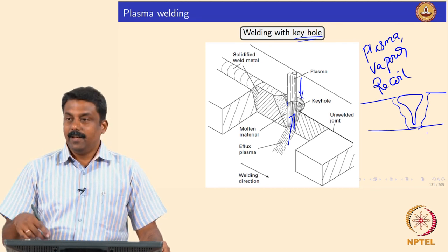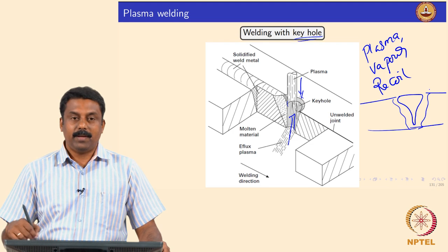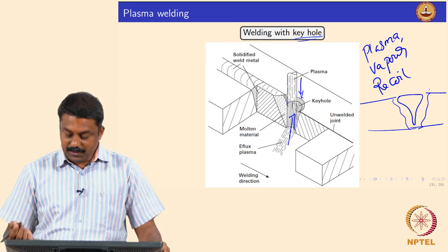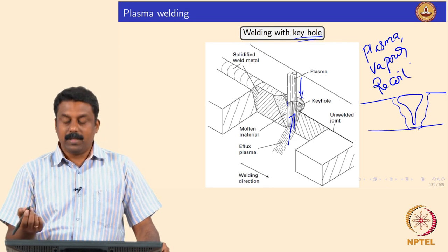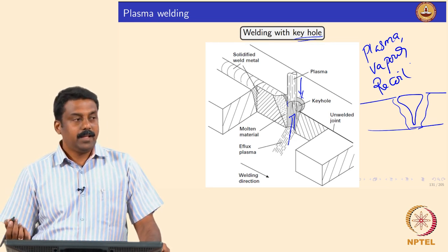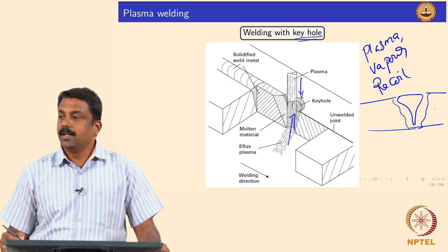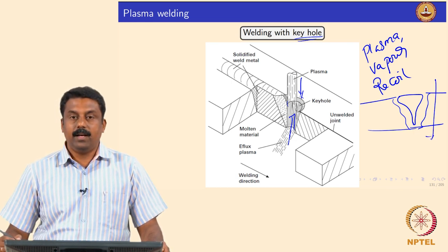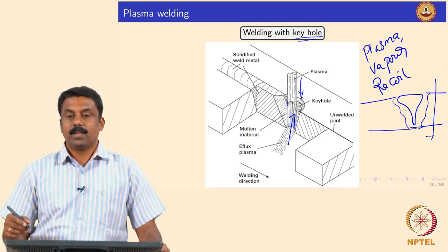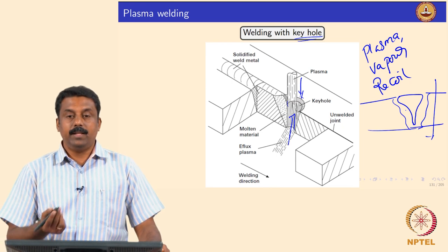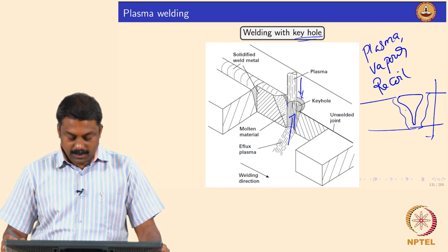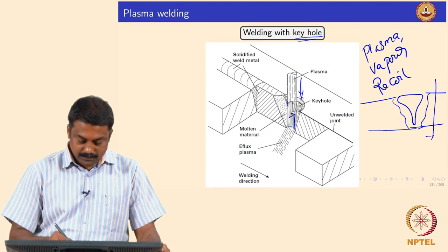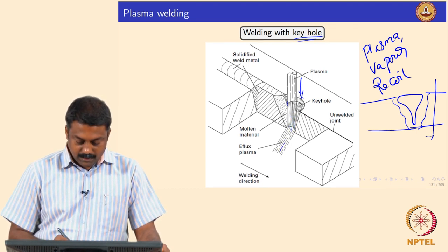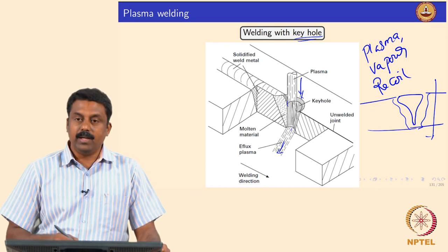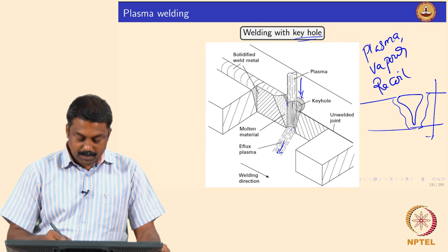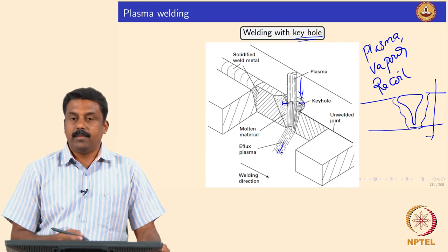When we look at laser welding, we'll see the keyhole formation mechanisms and force balances in great detail. Right now, we can assume that these three forces can also be generated with the plasma, and this is sometimes beneficial, because when you have a thicker section and you want a full penetration weld, you need to form a keyhole. The keyhole and its stability would determine the weld characteristics. That's what I showed you in this picture. So you have a plasma, and the vapor jet which is going out can create a recoil pressure, and the vapor pressure will also push the boundaries of the keyhole to open it up.